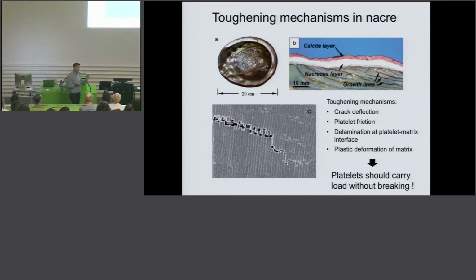So this is a very important concept here, that instead of propagating through and creating very flat surfaces, which would happen if the platelets were breaking, we rather have the platelets remaining intact, for most of them at least, and then the crack always needing to deflect at this interface, and that leads to this typical zigzag pattern and a lot of toughening mechanisms, some of which are listed here.